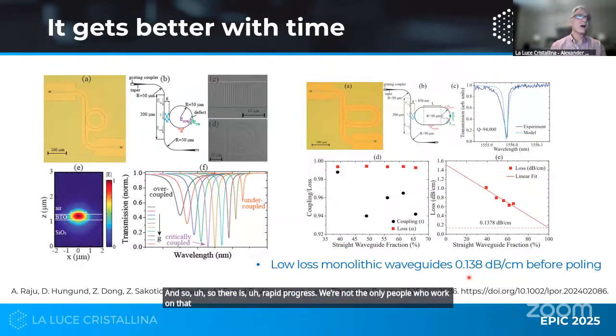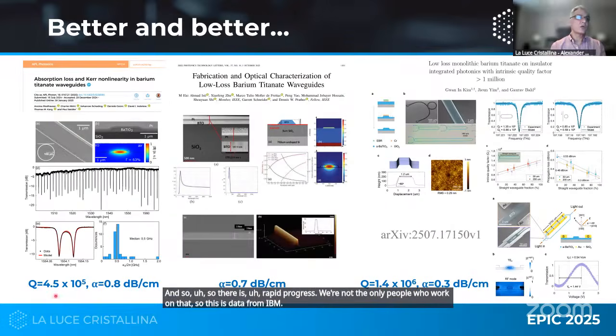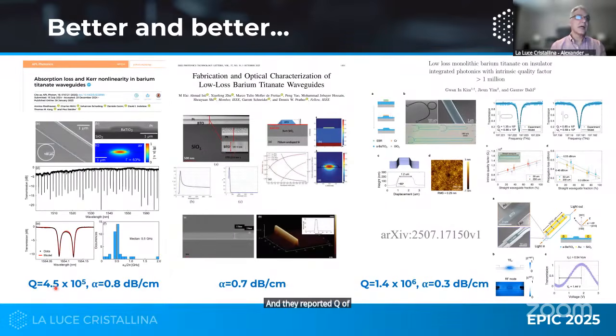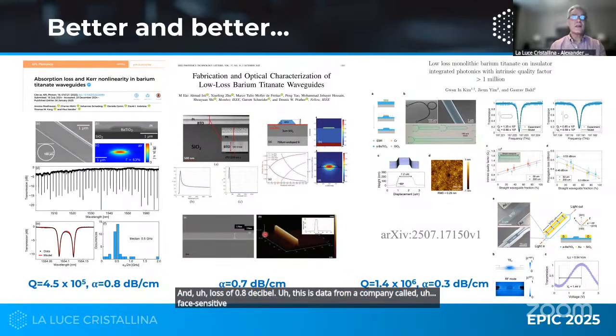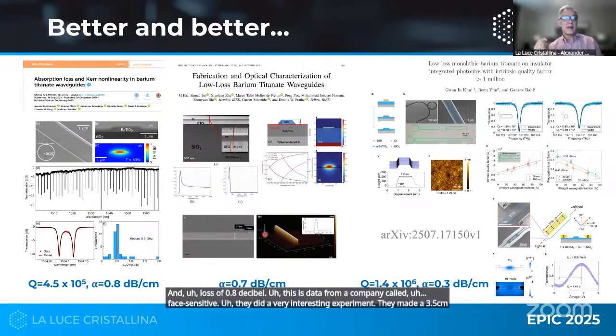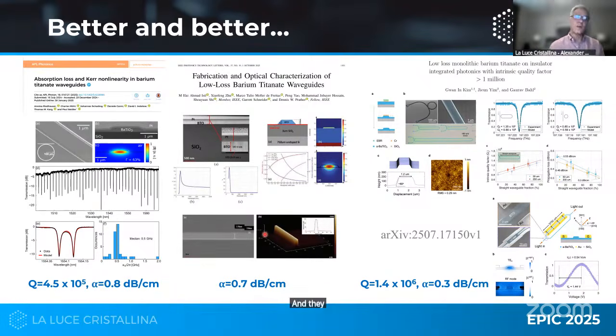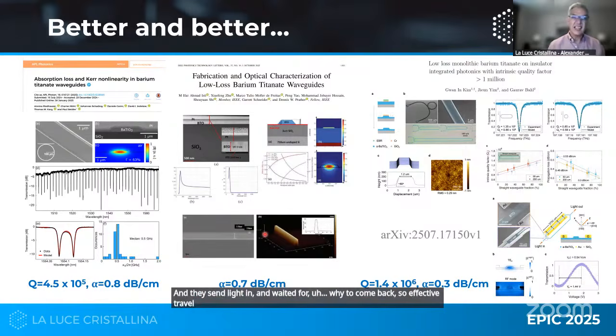So this is data from IBM, and they reported Q of 10 to the 5th and loss of 0.8 decibel. This is data from a company called Phase Sensitive. They did a very interesting experiment. They made a 3.5 centimeter long waveguide, and they sent light in and waited for light to come back. So effective travel length is 7 centimeters. So it's not millimeters, not microns, it's 7 centimeters. And they measured the loss of 0.7 dB.